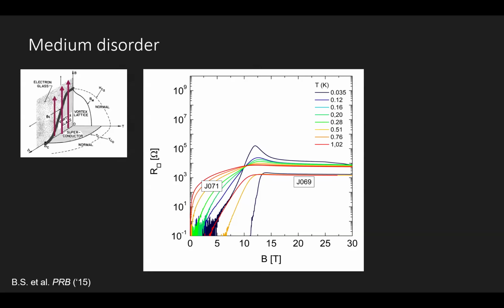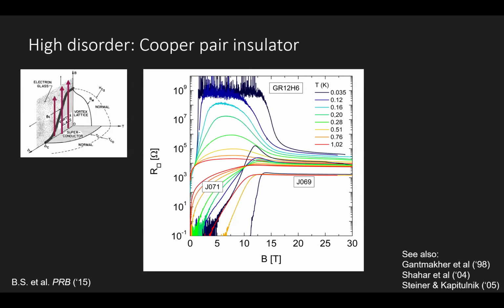Now, let's approach even more the critical disorder. What happens is a dramatic transition to a gigantic insulating state that you see here, which forms what was called in the field the Cooper pair insulator, which I do show here. There have been several pieces of evidence that this state is formed with Cooper pairs. People have done tunneling. There is a superconducting tunneling gap which resembles the superconducting gap of the superconducting phase. People have seen Little-Parks effects, coherent effects related to superconductivity.